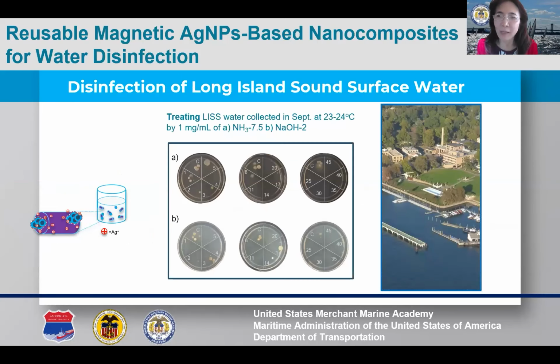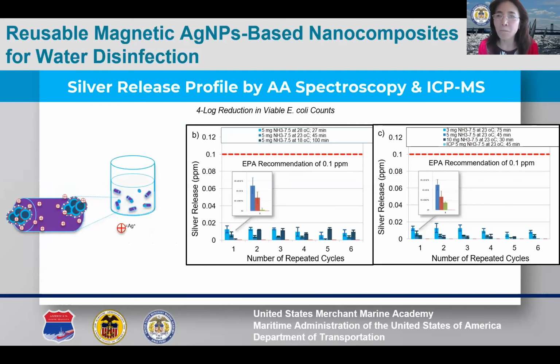The remarkable biocidal efficacy with minimum silver leaching can be ascribed to the nanocomposites' mesoporous silica shell surface, characterized by hydroxyl groups and a high degree of structural periodicity at the nanoscale, or smoothness. These features promote close association with bacteria and facilitate high local silver ion concentrations at the nanocomposite solution and the bacterial interfaces where biocidal actions take place.